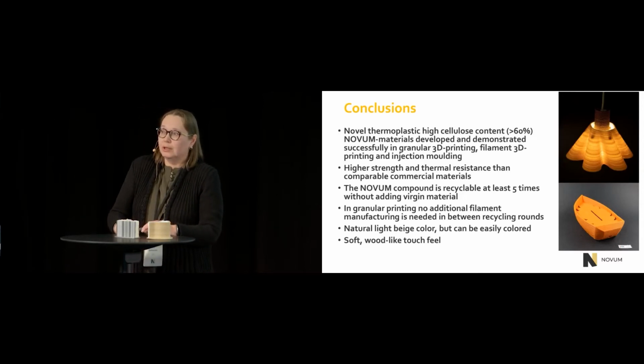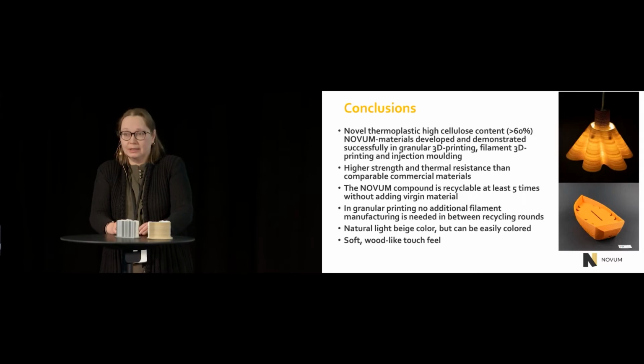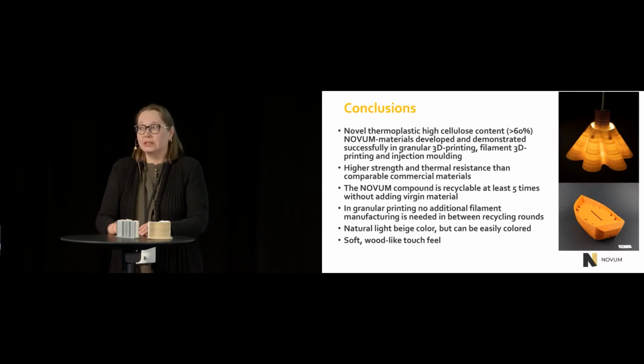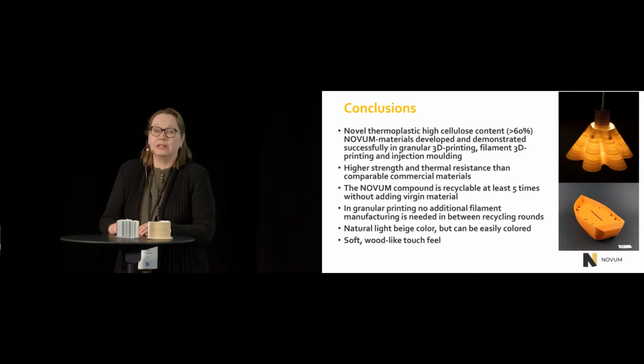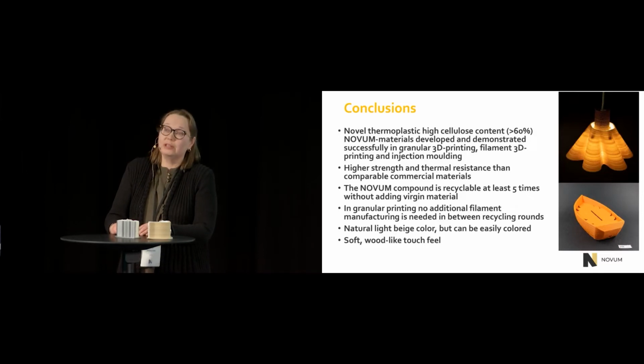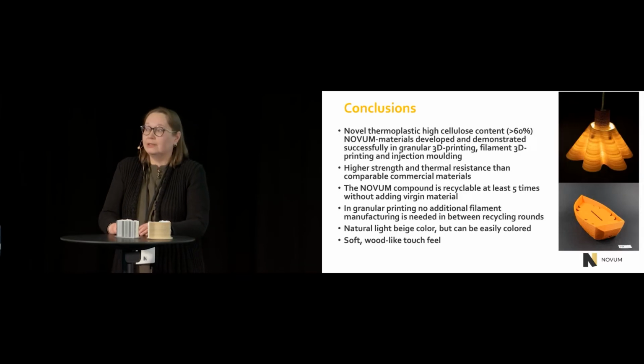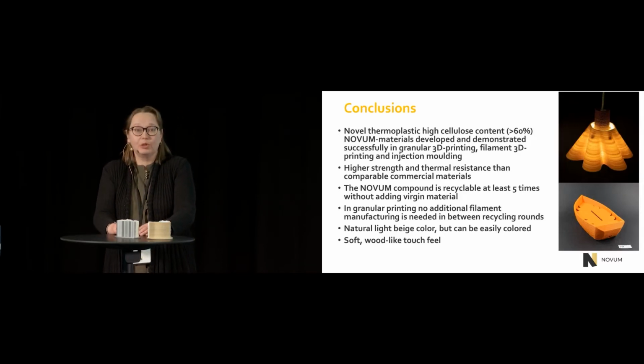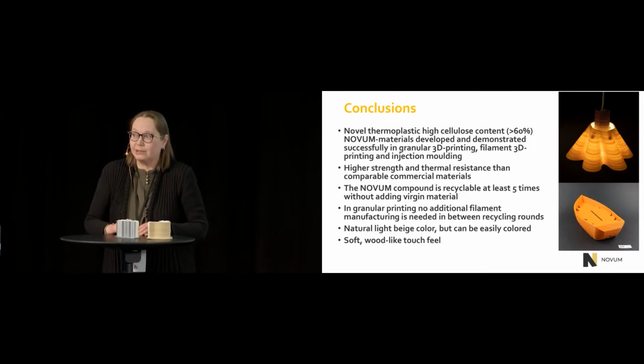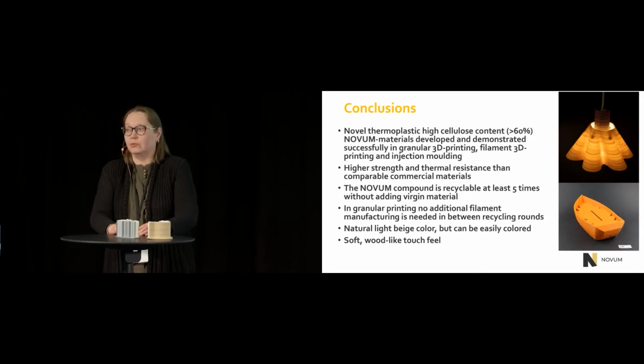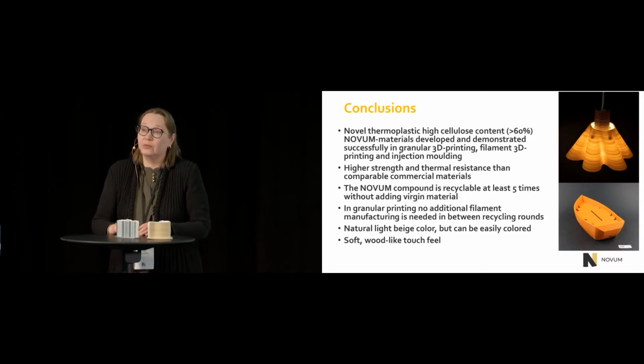And as a conclusion, we can say that we have developed within this NOVUM project a novel thermoplastic high cellulose content material and demonstrated it successfully in granular 3D printing, filament 3D printing, and injection molding. It has higher strength and thermal resistance than comparable commercial materials. The NOVUM compound is recyclable at least 5 times without adding virgin material. And when using this novel granular printing method, no additional filament manufacturing is actually needed in between recycling rounds.